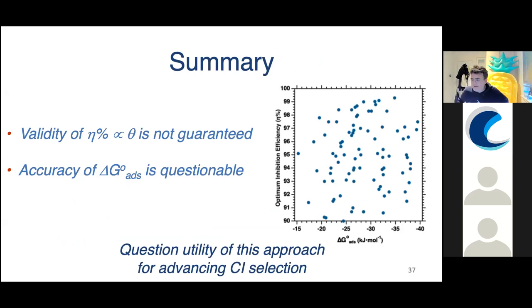So just to summarize, the validity of inhibition efficiency being proportional to theta cannot be guaranteed. How do we guarantee that? That's a tricky thing. Therefore, the accuracy of the delta G, the standard Gibbs energy of adsorption, is questionable, even if you use a more direct measure. So I think, as I say here, I really question the utility of this approach for advancing corrosion inhibitor selection.